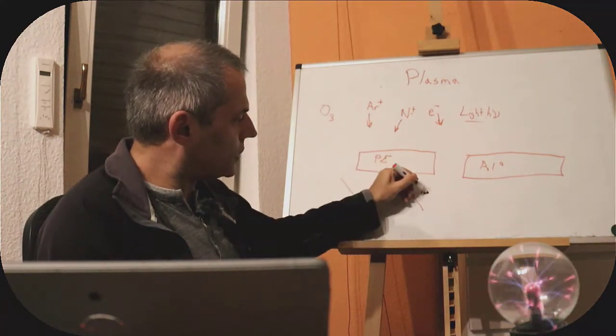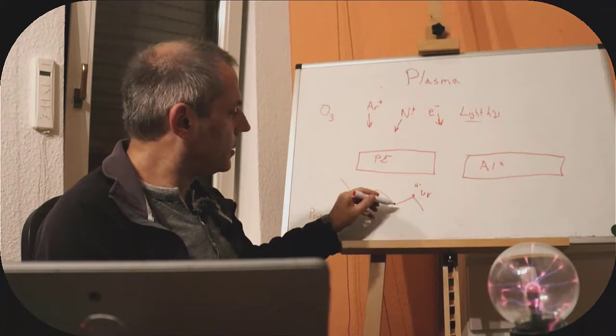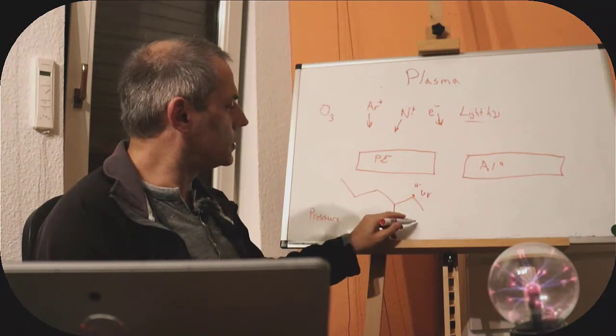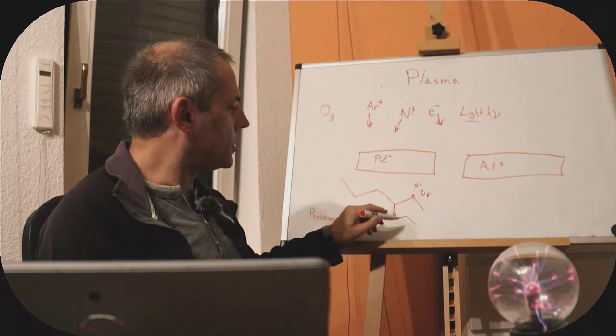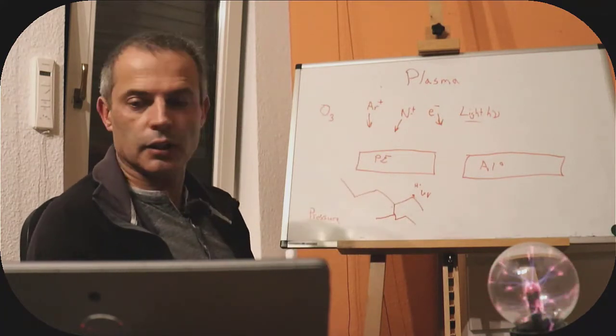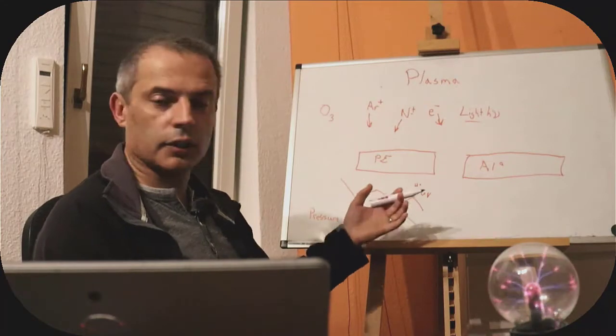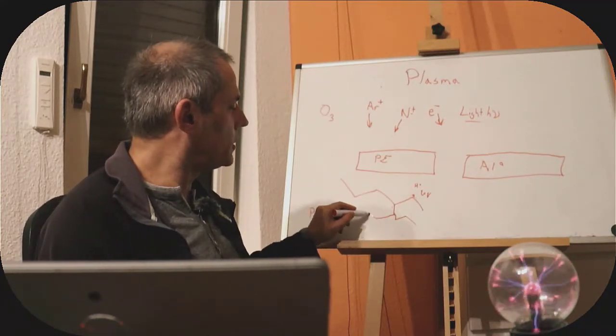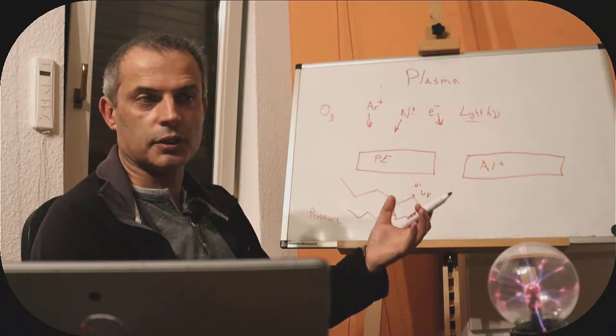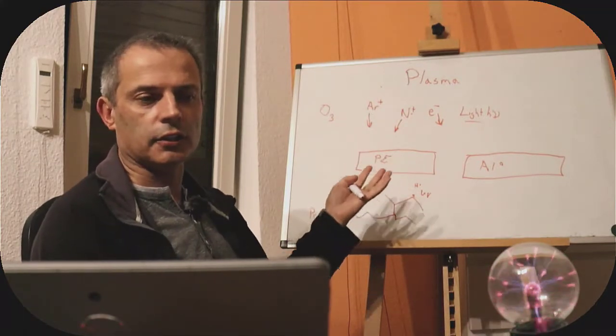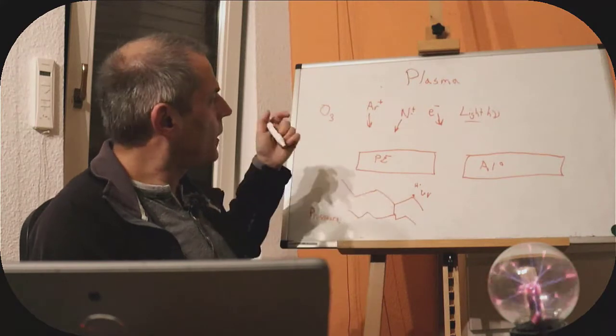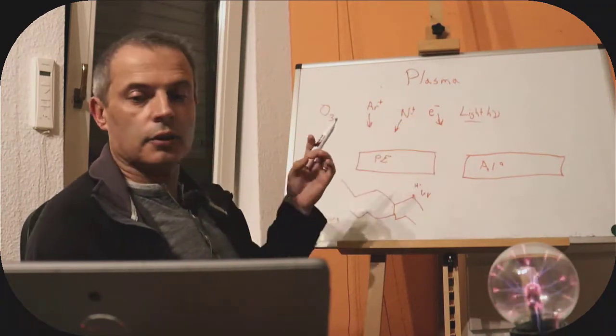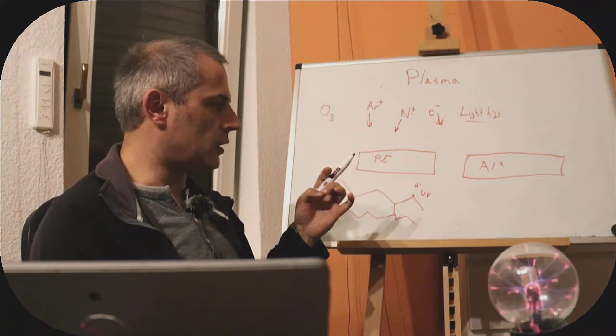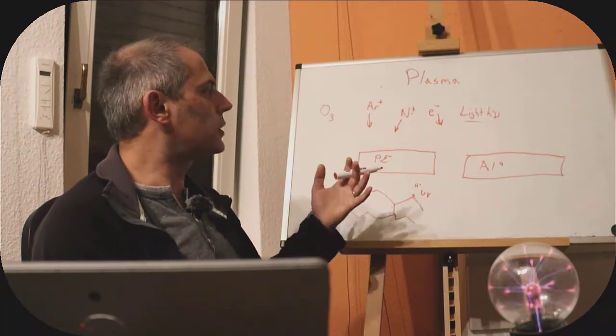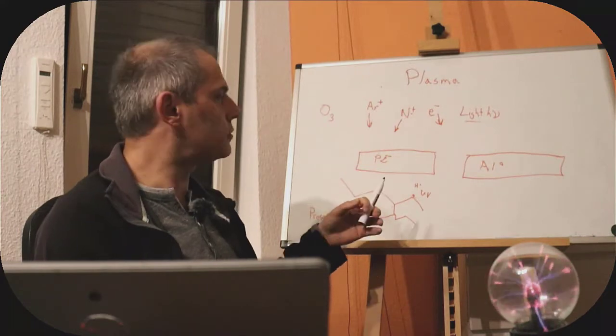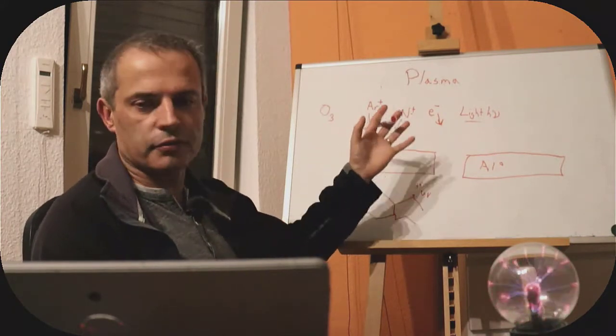That would be UV. The UV can also break the polymer, or it can cause it to cross-link. So if it hits somewhere in the middle, cleaves off a hydrogen, or it cleaves the backbone, it can rejoin, or it can attack a neighboring polymer chain and cross-link, making the polymer stiffer. This is what happens with aging of polymers if you leave them outside. Electrons will hit our surface, but they're comparatively not very aggressive because they are moving very fast, but they've not got very much mass.